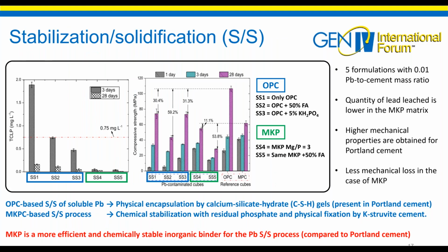The literature reports a lot of work on the solidification and stabilization of waste and hazardous materials. This is the case of Wong's studies, which is studying the stabilization solidification of lead-containing waste. In this study, he compared different formulations and types of cement: Portland cement, which is the most widely used cement in the world, and the phosphate cement. The results in the figure on the right show a significant decrease in the amount of leached lead when using the phosphate matrix. Compressive strength results show a decrease in performance compared to the reference.